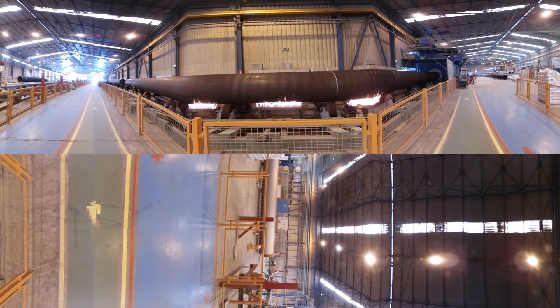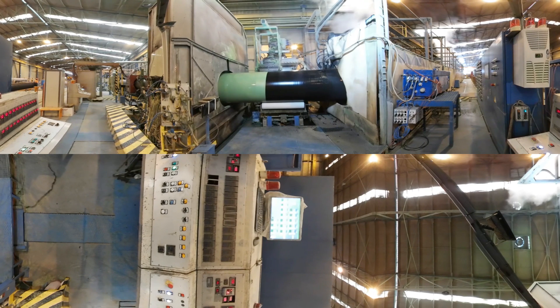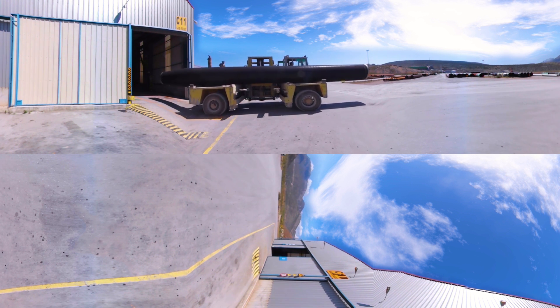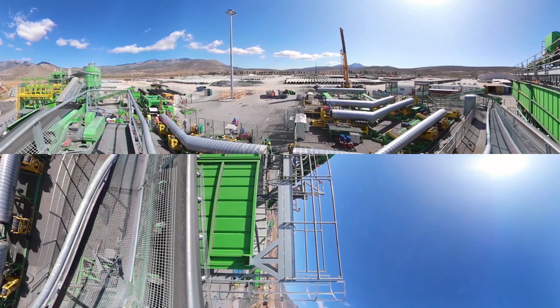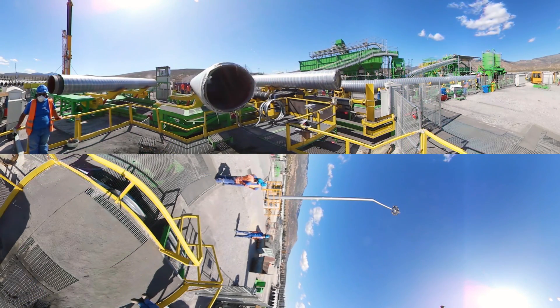Our plant in Thisvi, Greece, is one of a kind, with downstream operations like two external coating mills with the capability for anti-corrosion coatings such as fusion-bonded epoxy, single or dual layer, and three-layer polyethylene or polypropylene systems. One internal coating mill for internal liquid epoxy lining, and a concrete weight coating facility for offshore applications. The facility can produce anti-corrosion coating for pipe diameters from 8 to 40 inches, and concrete weight coating thickness up to 115 millimeters, with a maximum pipe length of 18 meters.